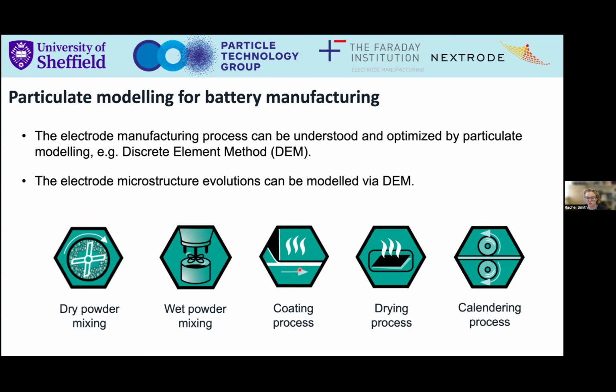We coat that onto a film. We then dry that film, and as everybody knows, that's quite expensive, drying that solvent off. And then we go through this calendaring process, which is effectively a compaction step. As Arno discussed, we're taking a relatively porous structure and reducing that porosity. Reducing that porosity is very important for us.